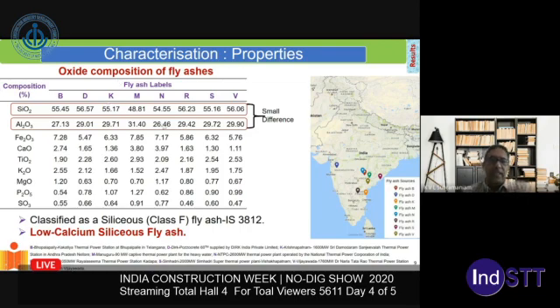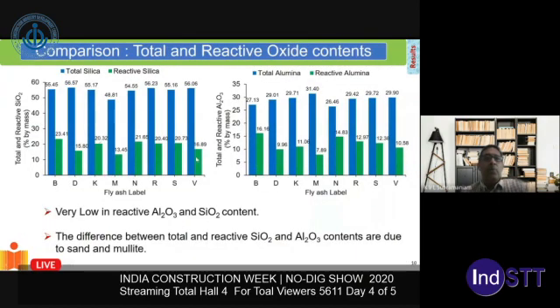So to understand that, we had to do a higher level of characterization. The one unique thing about fly ash that's produced in India, or I should say the fly ash that is predominantly produced in India, is that most of it has very low lime content. It's very, very low. So most of it is class F fly ash. Now, from characterization, we established the reactive silica and the reactive alumina in the fly ash. These are the two reactive elements in fly ash, which are most beneficial for use in cementitious systems or in alternate binders that are being produced nowadays.